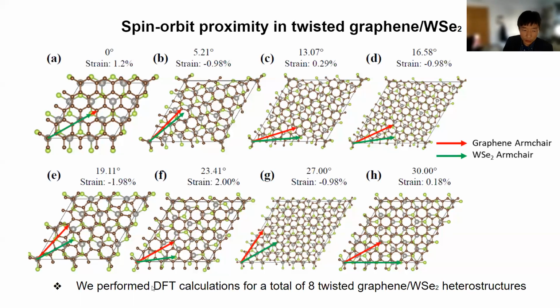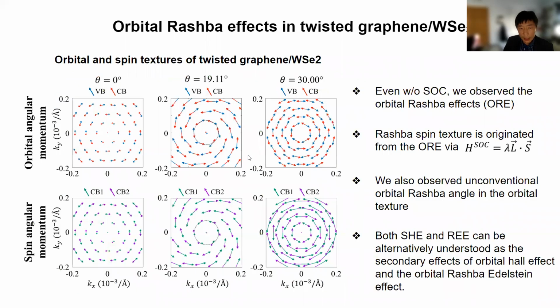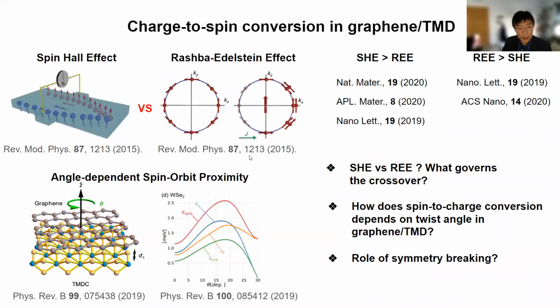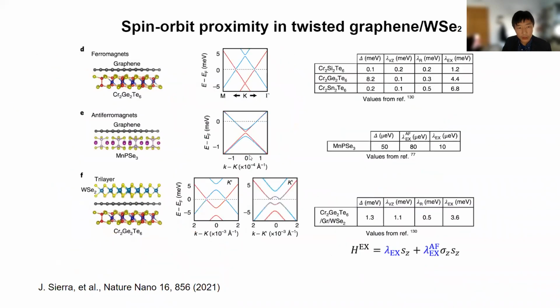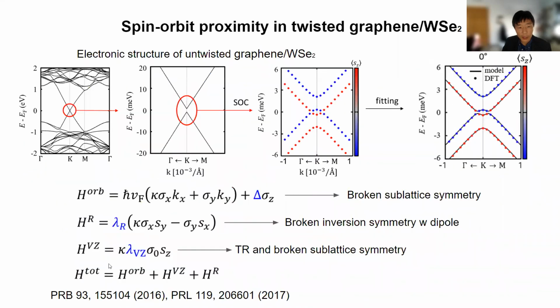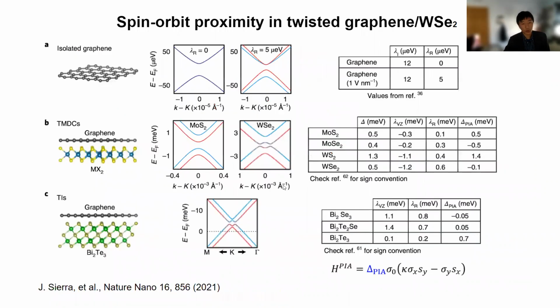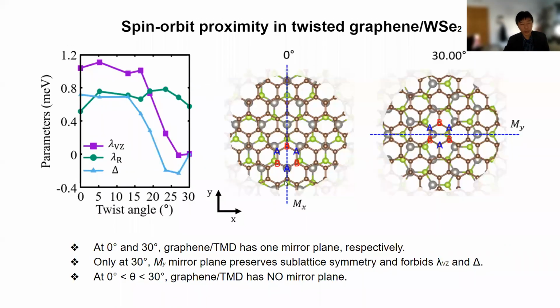So the first thing that we do is a DFT calculation of this material. And once we compute the band structure, we are able to feed it to this effective Hamiltonian that we have over here. And once we have this effective Hamiltonian, that will allow us to do the spin transport calculation.